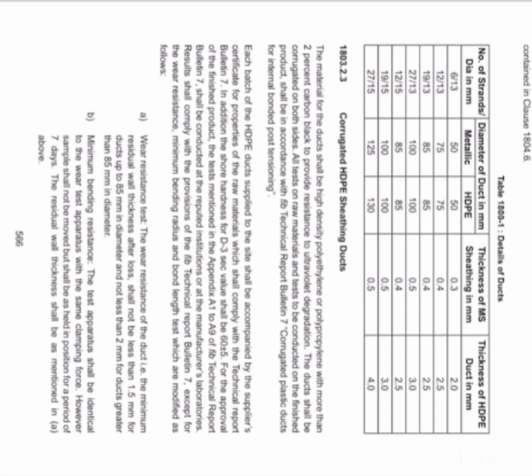Corrugated HDPE sheathing ducts: The material for the ducts shall be high density polyethylene or polypropylene with more than 2% carbon black to provide resistance to ultraviolet degradation. The ducts shall be corrugated on both sides. All tests on raw material and tests to be conducted on the finished product shall be in accordance with the FIB Technical Report Bulletin 7, corrugated plastic ducts for internal bonded post-tensioning.